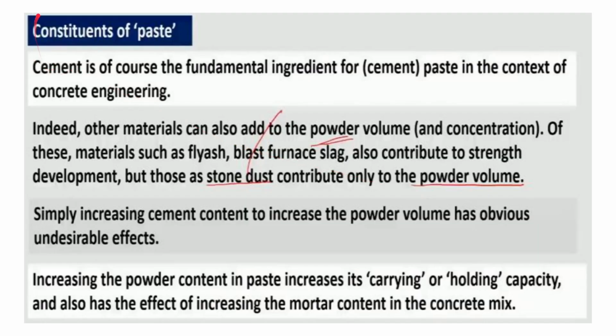So now let us go through the constituents of paste. Cement is of course the fundamental ingredient for cement paste in the context of concrete engineering. Indeed, other materials can also add to the powder volume and concentration of these materials, such as fly ash and blast furnace slag, which also contribute to strength development, but those such as stone dust contribute only to the powder volume, because the strength is mainly given, as you might know, by the calcium composition.